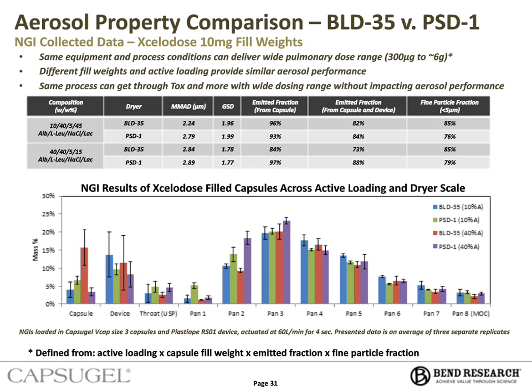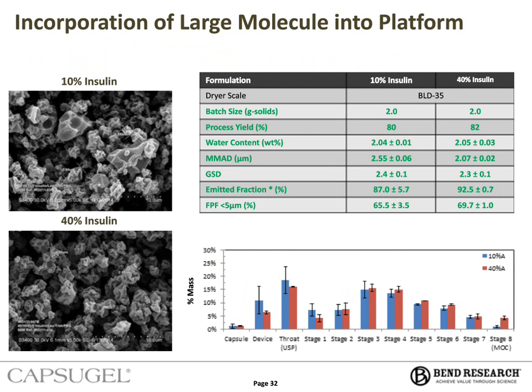And the last slide just shows the incorporation of insulin into this approach. So again, we have our lab scale spray dryer, 2-gram batch sizes, high product recoveries, which can be very important in the early formulation and process development stage, as a lot of these biotherapeutics can be extremely expensive at this stage and beyond. Water contents that are similar across active loadings, and again the aerosol performance, so very similar aerodynamic properties and deposition profiles as shown by the NGI results below.